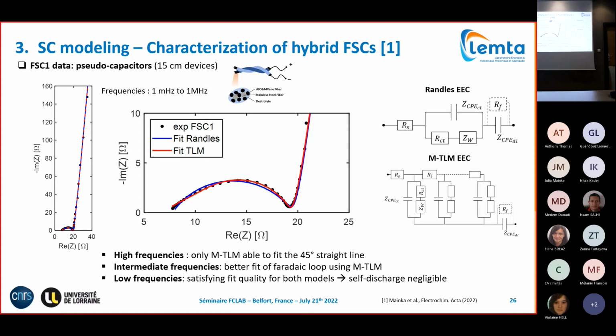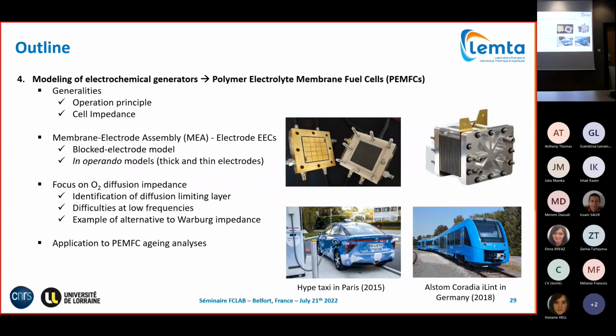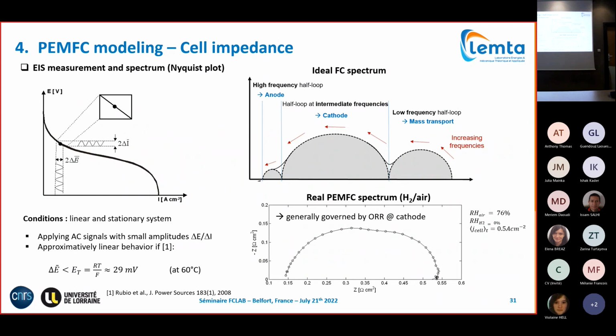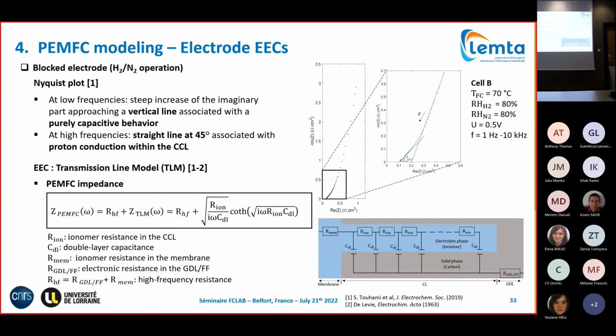So as long as online you think about questions, you talked very little about temperature and the influence of temperature on behavior and aging, and also the parameters of systems vary a lot with temperature. It's easy because we did all we possibly could to impose constant temperature. So we did not analyze this influence. Our PMC analysis was always at 80 degrees. So for the aging analysis, 80 degrees, because this was mentioned in the AST, if you want to have accelerated stress for cycling at 80 degrees. So all our analyses were run at a constant temperature. But actually it is possible. It's easy to measure and compare different spectra measured at different temperatures.